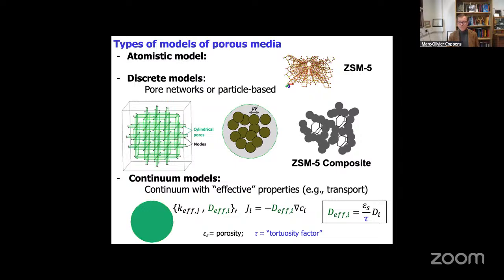And so this effective diffusivity needs then to be related to the diffusivities in the actual pore space. And so that would be D_i here on the right. And the effective diffusivity is then related to this diffusivity through the fraction that is occupied by pores, so the porosity, epsilon_s.